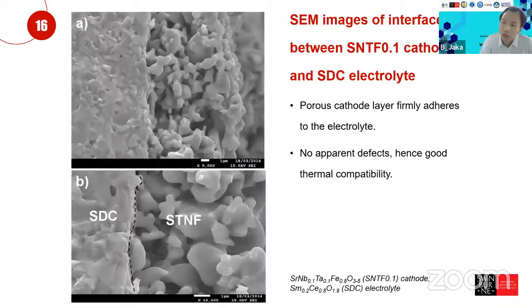This shows the interface between the STNF 0.1 and the SDC electrolyte. Okay, so we see that there is no problem after we sinter the fuel cell components, after we attach the STNF cathode onto the SDC electrolyte.